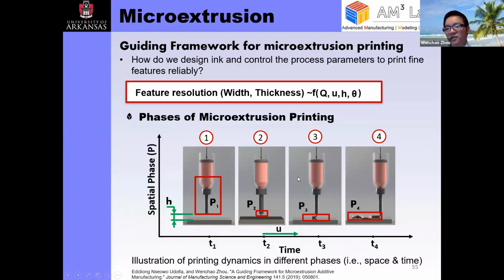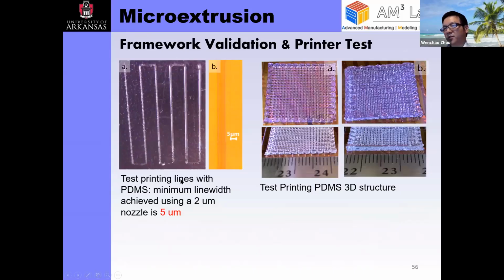So this printing process seems to be very simple because it's just a syringe you push out, you print, but it's actually quite complicated. It's very difficult to get a successful printing, and this is one of the reasons why we studied the fundamentals of this process and divided it into 4 different phases. We developed equations to describe these different phases of printing and guide the printing process. Due to time, I'm not going to get into details of that, but we successfully printed some PDMS with a nozzle size of 2 micron and printing resolution of 5 micron.